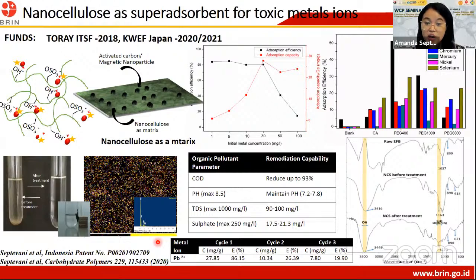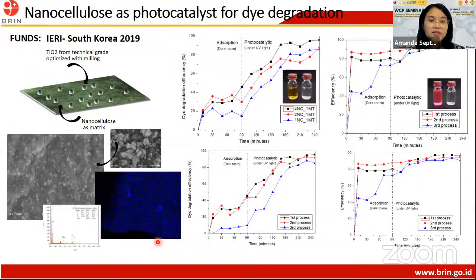In terms of reusability, we also did some testing, and we can see that after 3 times use of our polymer composite, it can still maintain its capability of absorption towards metals. The second one is about the photocatalyst for degradation. We introduced titanium oxide in our cellulose matrix, and it can degrade the dye, in this case methyl orange, by more than 90%. And for rhodamine B, because it is a less complex dye structure, it is really easy to degrade, even in less than 10 minutes. And in terms of reusability, again, our composite can be used up to 3 times.